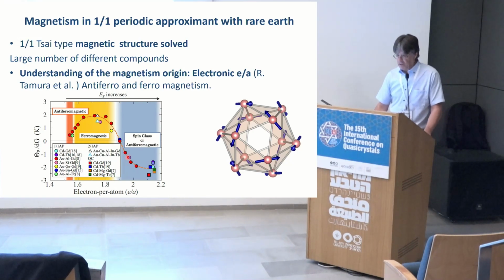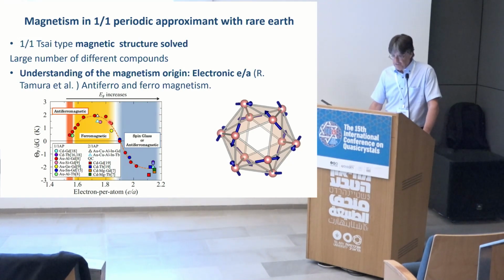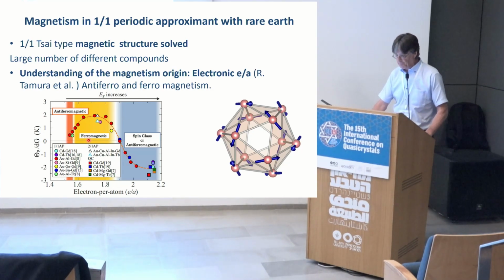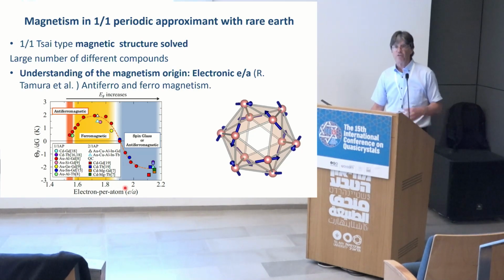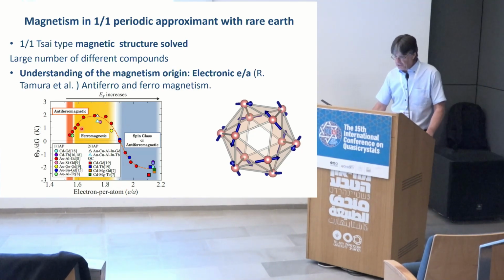They did even more. They studied a lot of different samples and could have a good understanding of what is the origin of the magnetism. And the origin of the magnetism is the ratio e over a, where e is the number of electrons and a is the number of atoms. And you see you have a region where it's antiferromagnetic, a region where it's ferromagnetic, and a region where it's spin glass.